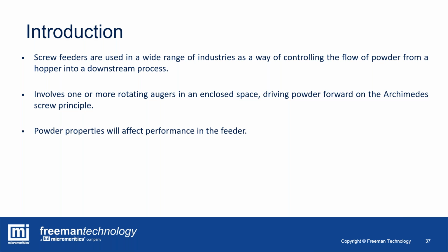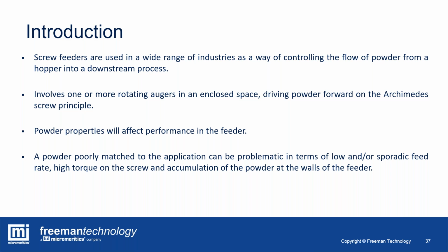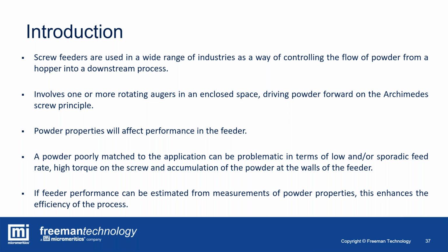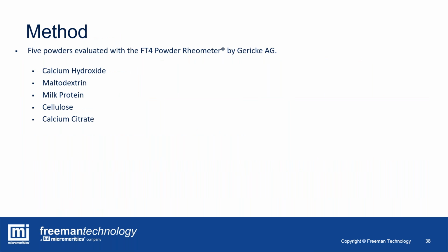Powder properties will affect the performance within the feeder. If you've got a powder that's poorly matched to the application, it can be problematic in terms of low and/or sporadic feed rates. It can present high torques on the screw, and you may find you get accumulation of the powder at the wall of the feeder. However, if feeder performance can be estimated from measurements of powder properties, this enhances the efficiency of the process, of course. So what we did in this study was took 5 powders and we evaluated them with the FT4.